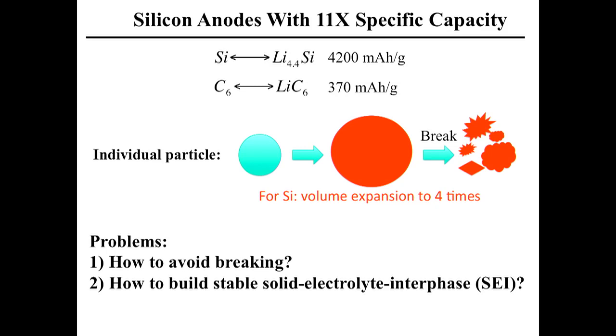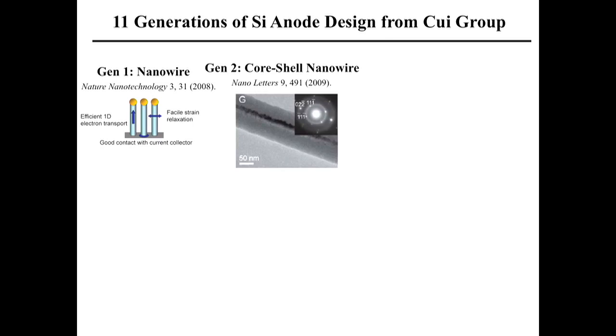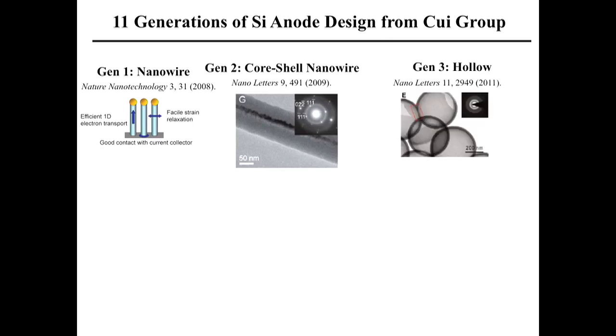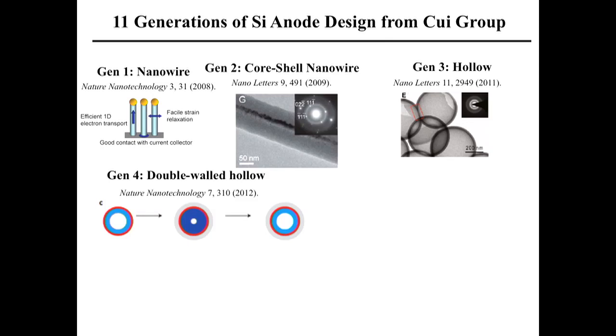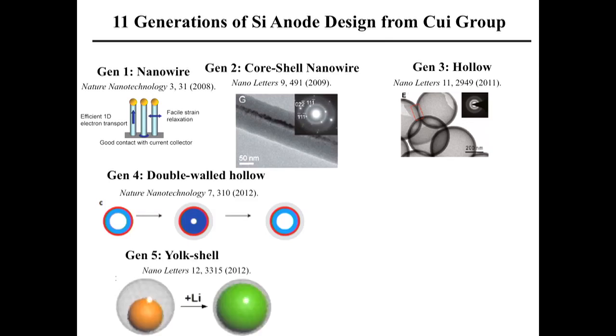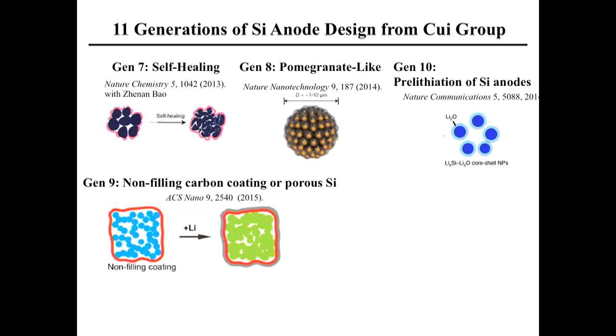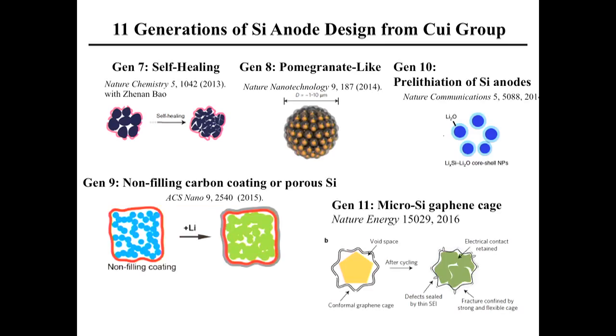So we learn a lot. So let me give you a quick 10 years of research, right? Into 2 slides. Well, we use nanowire. They're small enough, they don't break. And then we do coarser, it's more stable. And then we do hollow, even more stable, but no stable interface. And then we design double wall hollow structure. It just keeps coming. Now we are at 11 generations. So that's my 10, 11 years at Stanford. So that's what I did. So 2 slides. But let me highlight a few to share with you the thinking.